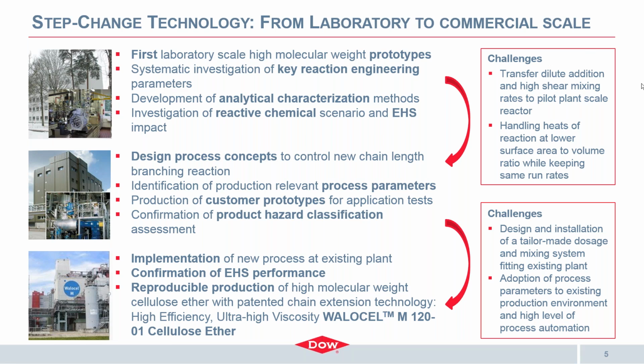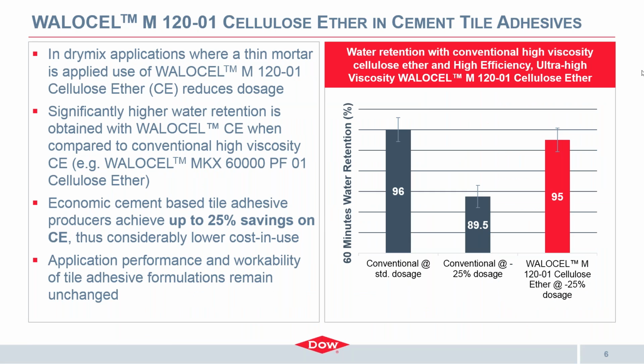And let's have a quick benchmark here of the WALOCEL M 120-01 and compare it to some regular high viscous cellulose ether from the market. The graph on the right tells it all basically. It shows the gray one is the standard product and the red one is the WALOCEL M 120-01. If you look at it, water retention of a regular cellulose ether at some standard dosage is 96%. That's fairly good. But as dosage is reduced by 25%, we end up with a significant drop to only 89.5%. That's a significant difference.